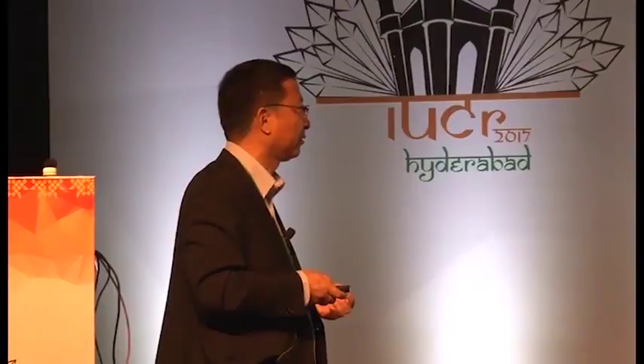For the molecules, we investigated the magnetic relaxation. The energy barrier for the molecules is around 300 Kelvin. And we can observe the hysteresis loop.